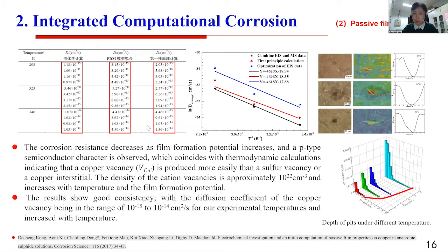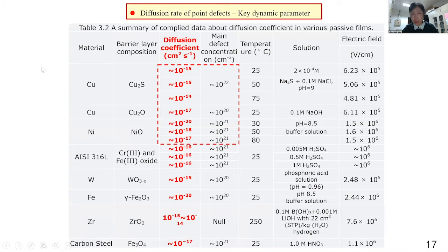in this system. We also published the paper in Corrosion Science, and after that we tried to use this method to calculate different kinds of passive films. In the various passive films, the diffusion coefficient changed greatly, so we can use the diffusion rate of the point defect as the key dynamic parameter.